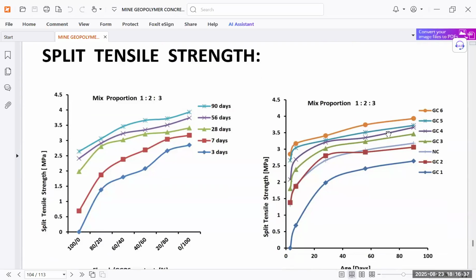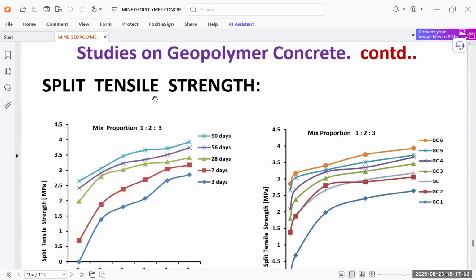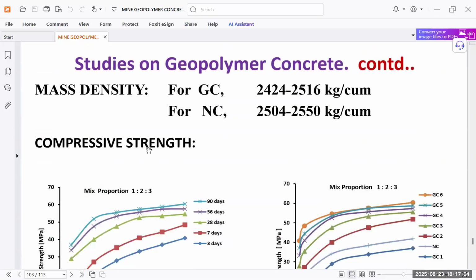You can see that GC6 has a good split tensile strength compared to normal concrete. In this case of different ratios, you can see the differences for 90 days. This is the strength for mix proportion 1:2:3. So geopolymer concrete is showing not only good compressive strength but also good split tensile strength. This is split tensile strength, and this is the compressive strength.